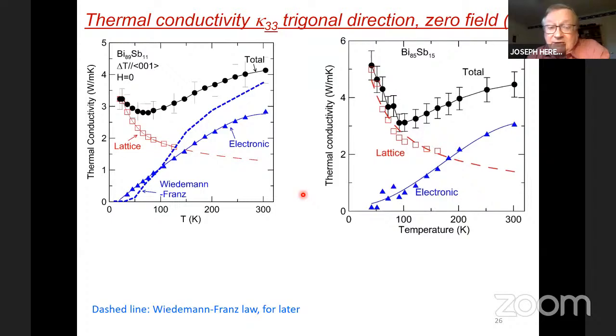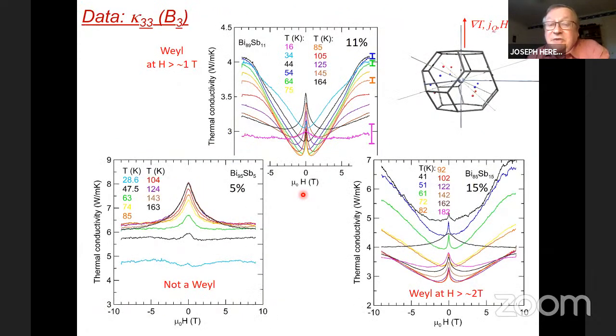Now, let's go straight to the main data. So we now measure, we flip the field from bisectrix to binary direct to trigonal direction, B3, longitudinal magnetothermal conductivity. And we do this on the sample at 5%, which has trivial pockets, and the sample at 11%, which doesn't, and the sample at 15%, which doesn't.